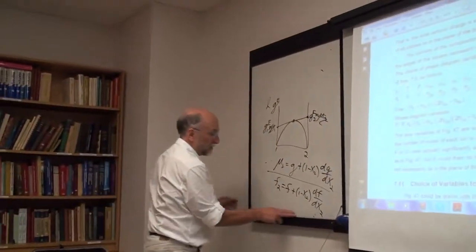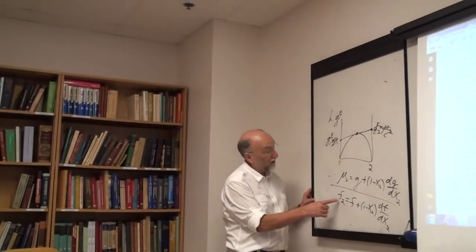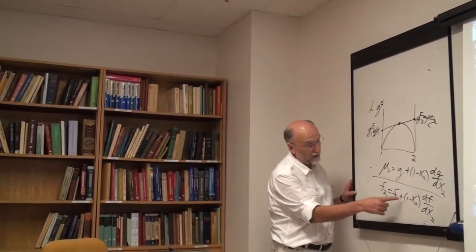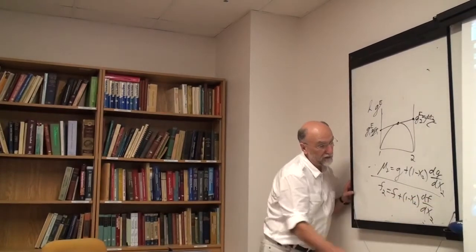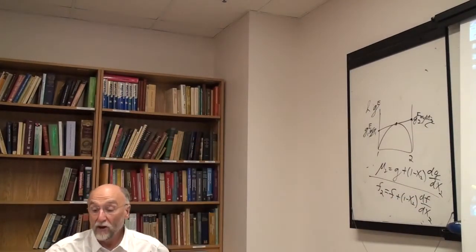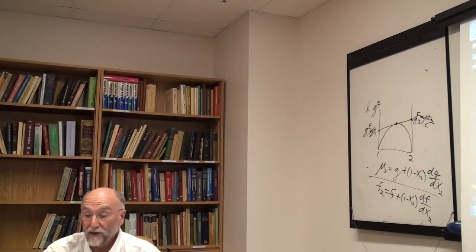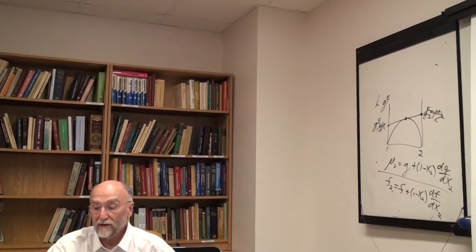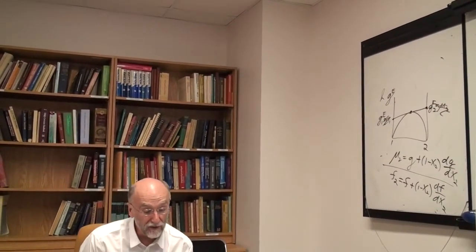And this is the easiest. This is the easy expression to use. Any partial property or excess partial property of component 2 is equal to the corresponding integral property plus x1 times the derivative of the integral with respect to x2. So if you have f as a polynomial, as you do in equations 168 and 169, you can then calculate the partials as you have in equations 171 to 174.